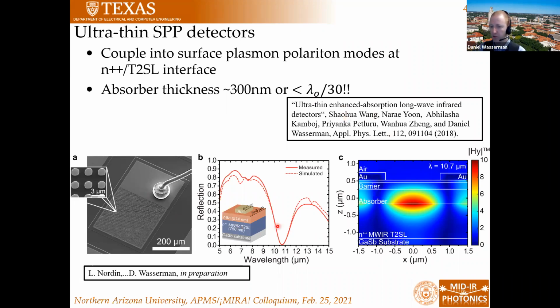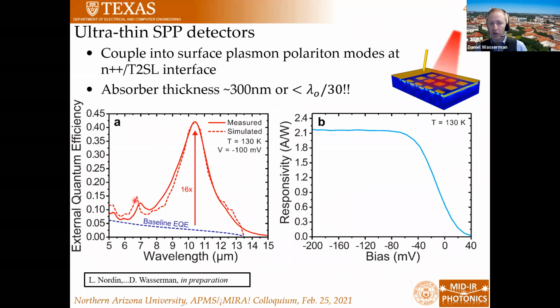But now we've grown the structures and we've characterized them, and this is what the mode looks like on resonance. You can see that we're coupling into a mode that is bound to the plasmonic detector interface. So you have a very, very strong confinement of your light. And if we look at the quantum efficiency, you can see this is the quantum efficiency for our fabricated detector. This is experimental data in solid, and the dashed data is our COMSOL simulations. And this is the external quantum efficiency that you would get if you got rid of the coupling antennas, if you got rid of the plasmonic material. So we have a 16-fold improvement in our absorption efficiency, and we're absorbing above 42% of our light. Not even that, we're absorbing more than that. We are converting 42% of our light to a useful electrical signal in a detector that is lambda over 30. So it's 1/30th the thickness of the wavelength of our light.